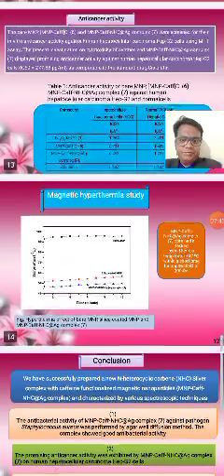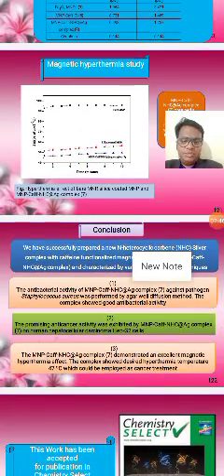We evaluated it for the magnetic hyperthermia experiment. This is the temperature kinetic curve, and it shows that it induces a therapeutic temperature of 42 degrees Celsius, which is sufficient to kill the cancerous or infected cells without affecting the normal cells.